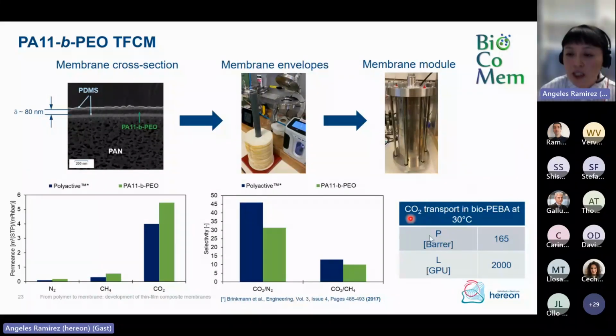And now we can see here, in this little table showing the transport properties of carbon dioxide through this polymer at 30 degrees, that from an initial permeability coefficient of 165 barrer, which gives us the potential application of the polymer to be used as a membrane, we get a final permeance of around 2000 GPU when this polymer is used as an ultra thin layer in a composite membrane of around 80 nanometers thickness.